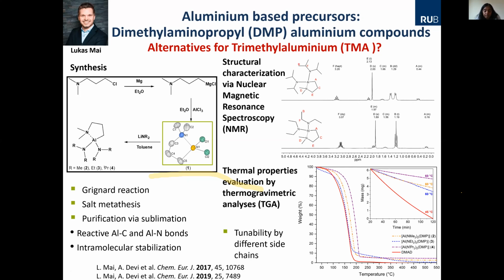This is a good sign, showing that the precursor can be evaporated undecomposed, and it's exactly what we need in a CVD and ALD process, because you have a bottle where the precursor is stored, you heat it and bring it to the gas phase to the reactor. At the deposition zone, it should react, not before. So from this graph, we can see that the precursor sublimes or evaporates without any decomposition, which is a good sign. That is the first important parameter, apart from the purity, that we have to investigate.